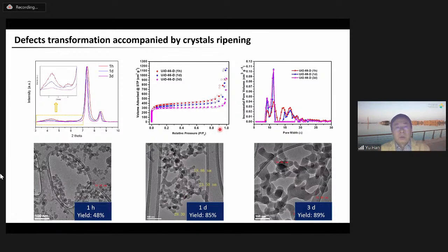So correspondingly, the total pore volume becomes smaller, and the pore size distribution associated with the missing cluster defects gradually disappears. More interestingly, with the extension of the crystallization time, the crystal size, as you can see, also increases. So taken together, the structure defects evolve during the crystallization, while at the same time, the crystal undergoes a ripening process. Okay, so all this information can only be obtained with TEM study. The UiO-66 system has been extensively studied, but this kind of information can only be provided by